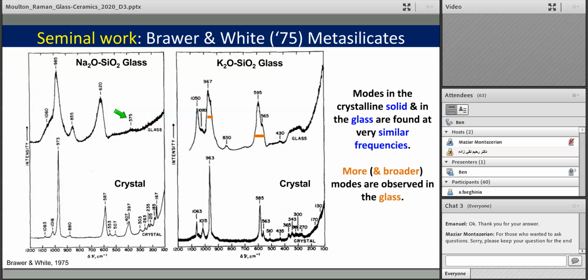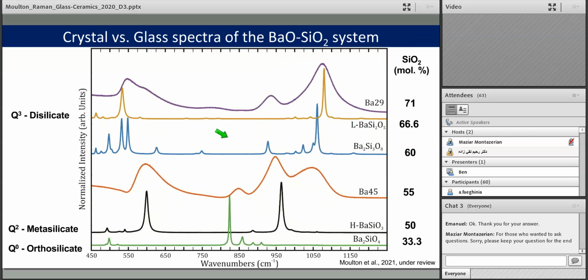For instance, this peak is quite a bit broader than the peak in the crystal. Same goes for this peak. We see that the peaks in the glass are significantly broad, and we also see some extra peaks in the glass that are very weak or non-existent, for example, here in the crystal. So there are many similarities, but some differences, and usually the differences produce more vibrational modes in the glass spectra.